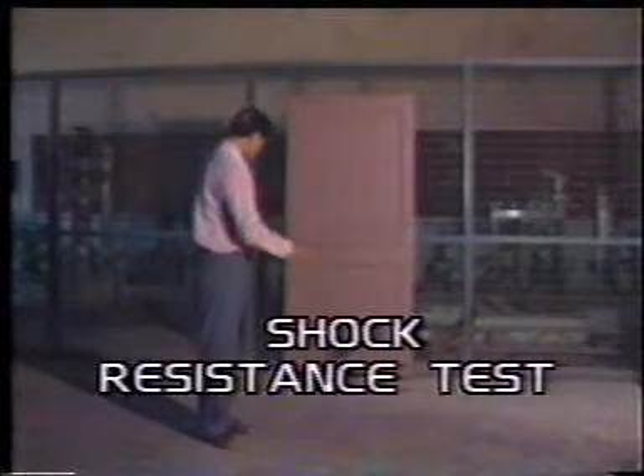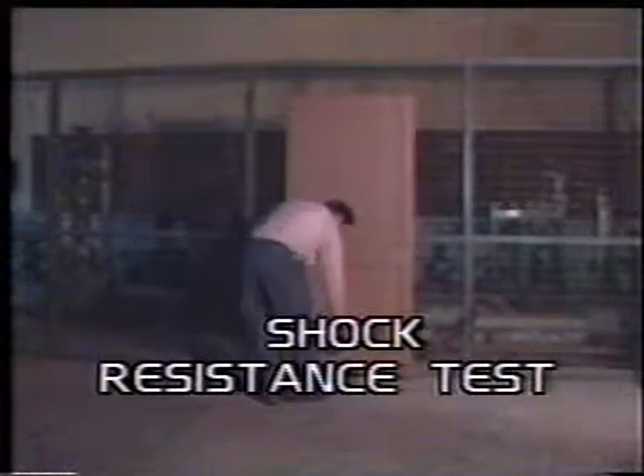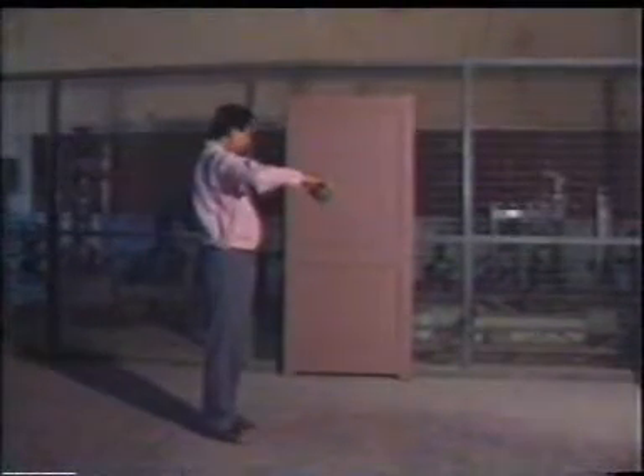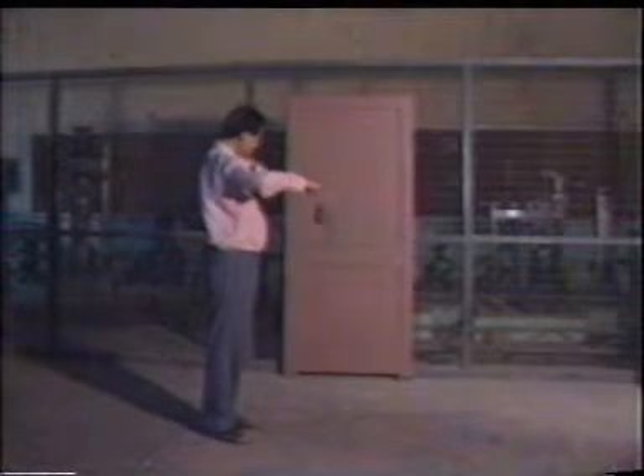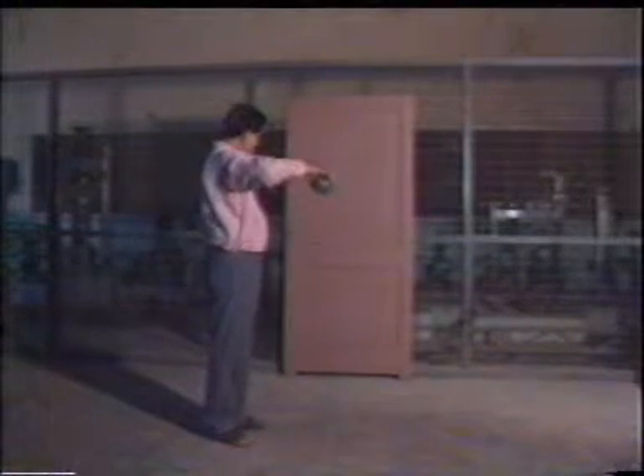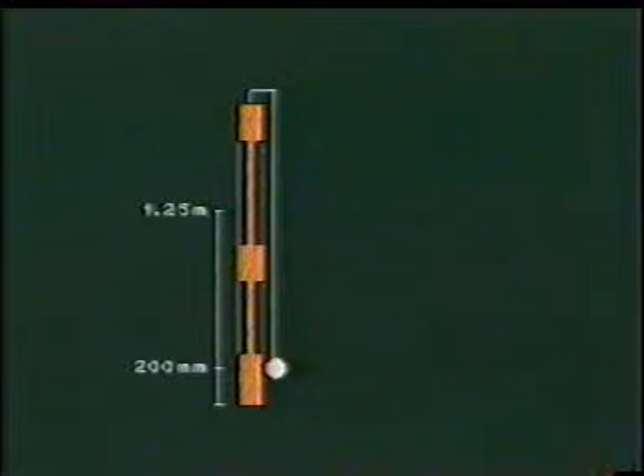The last lab test is the shock resistance test. A leather ball of 20 centimeter diameter filled with sand weighing 5 kilograms is made to swing and hit against the door 15 times. The general condition should be checked after every 5 blows. There should be no visible damage after 15 blows. The ball should be lifted up to a height of 1.25 meters above the point of impact, which should be 200 millimeters above the bottom of the door.